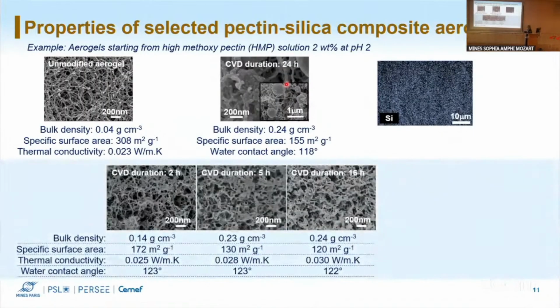We continued further by adjusting the duration of chemical vapor deposition, again for this formulation: 2 hours, 5 hours, and 16 hours. In this case, the bulk density increases with longer deposition time. The surface area decreases. Thermal conductivity increases as well. The contact angles, we can say, stay almost stable regardless of the time.